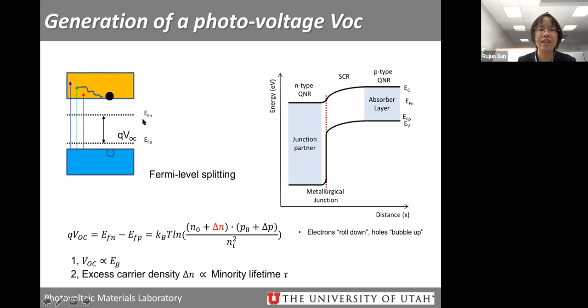But how do we describe the behavior of electrons and holes in a material? We use the Fermi level. Under illumination, we have quasi-Fermi levels, which are different for electrons and holes. We call this the Fermi level splitting. Why is this important? Because when we shine light on the solar cell, the photo-generated carriers will be transported: the electrons will transport to the n-type, and the holes transport to the p-type, and then they are extracted by the electrodes. So the chemical potential of holes and electrons is the difference of the quasi-Fermi levels. This is related to the excess carrier, especially the minority carrier.